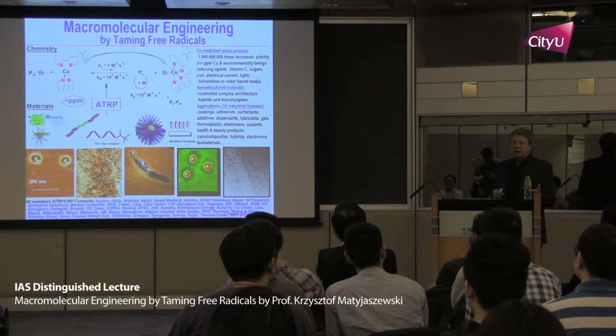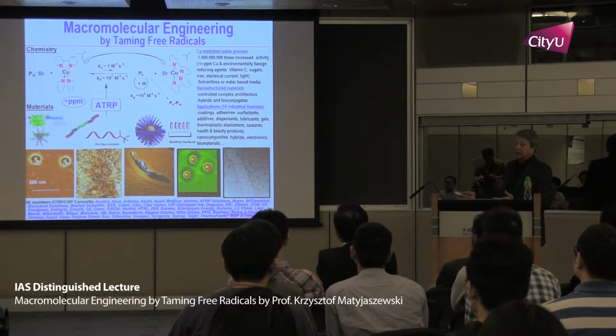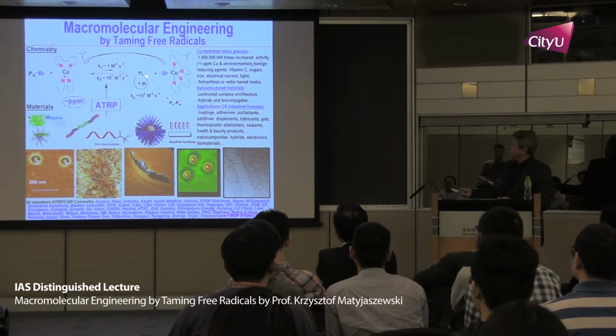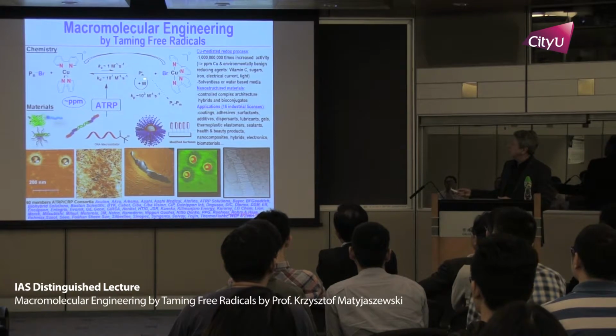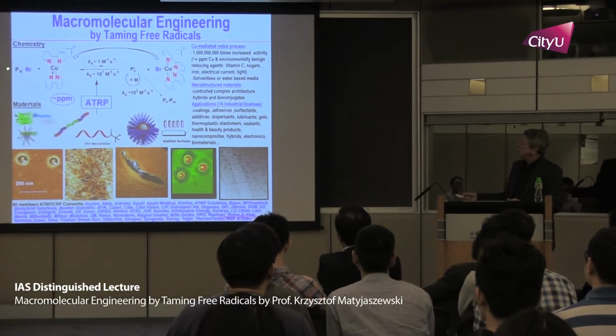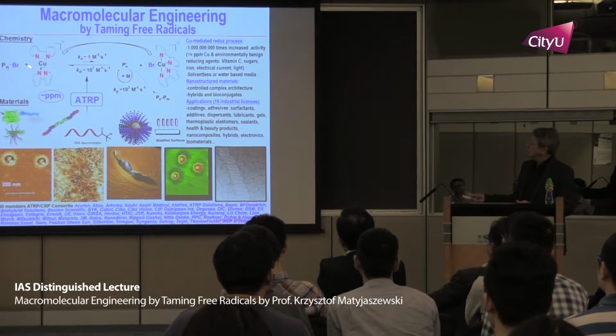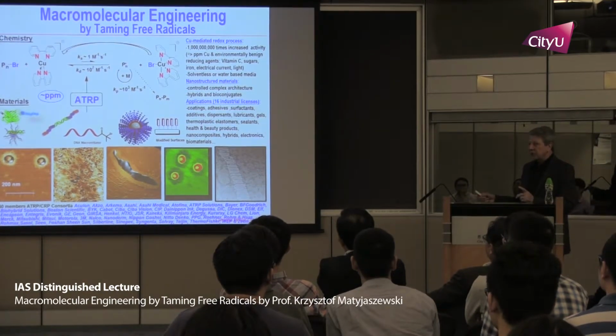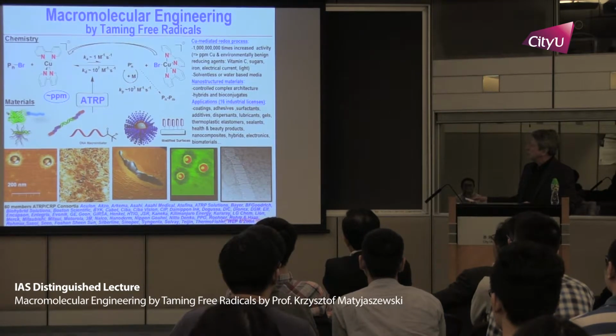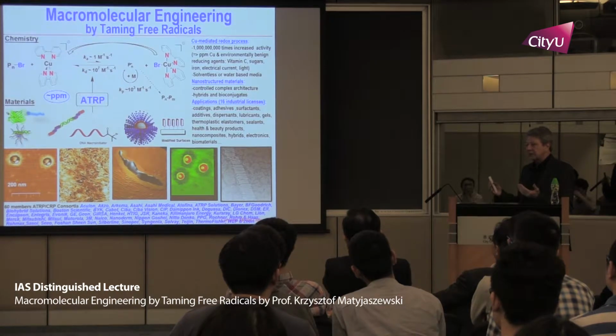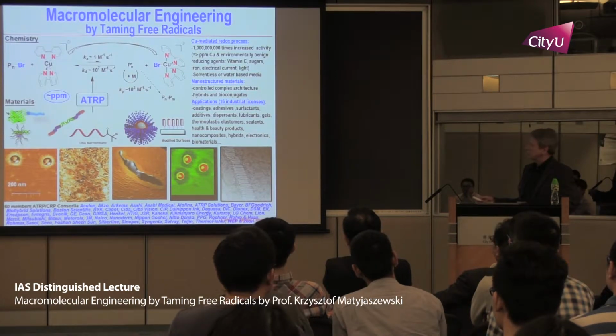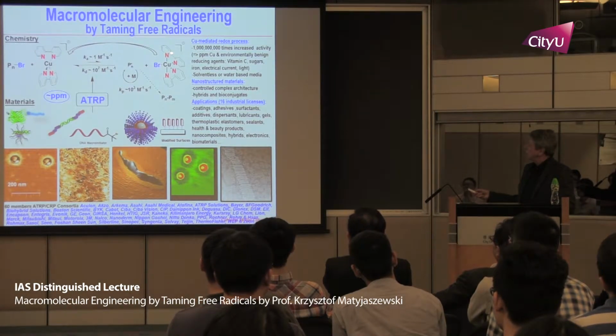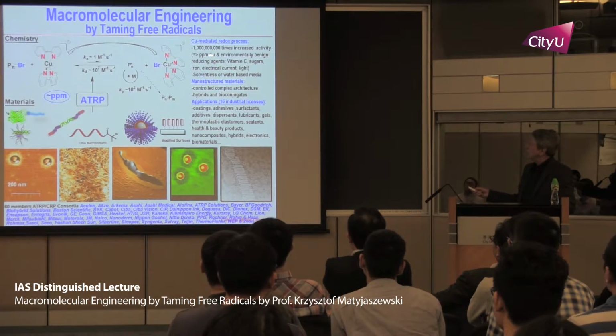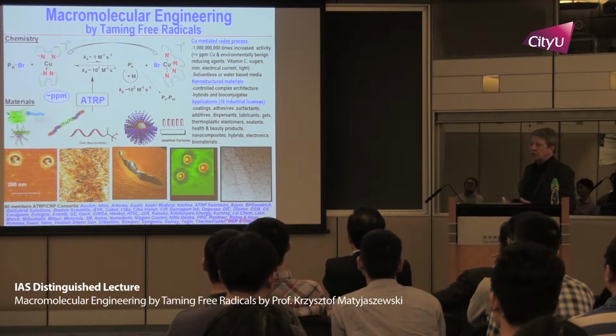So you need to extend the life of the propagating chain from 1 second to hours. We do that by equilibrating these active free radicals with dormant species, in the presence of catalysts. This is a very special catalytic system because it involves both an activator and a deactivator, so two states of a catalyst are needed. As you will see later, we borrowed some concepts from organic chemistry, but then we developed catalysts which are now 1 billion times more active than the original catalysts.